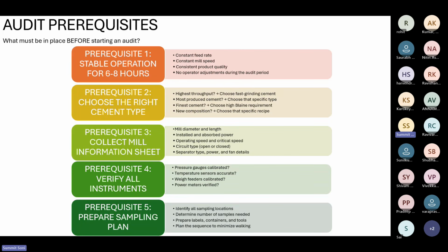Fifth prerequisite is we need to identify all the sampling points and all the flow measurement points as well. When it comes to cement grinding, especially the ball mills, there is no set parameter for laying down the ducts. There are instances where the mill outlet duct goes right away into the separator. There will be a span of, let's say, 5-6 meters. Then from the top of the separator, it enters the bag filter right away, or goes through a fan. Because of the space constraint and the cost optimization that the mill supplier wanted to do, we don't have a lot of space in a lot of cases to correctly measure the flow of the air in the ball mill section.